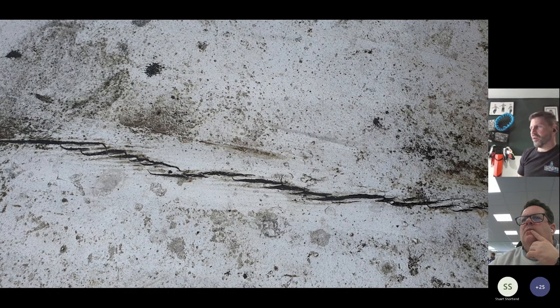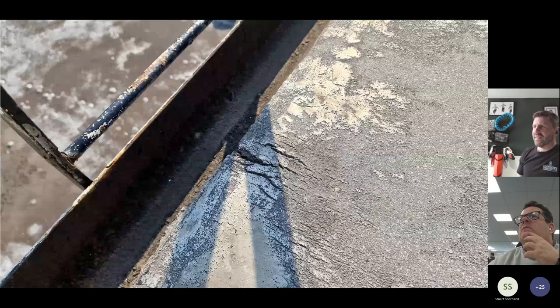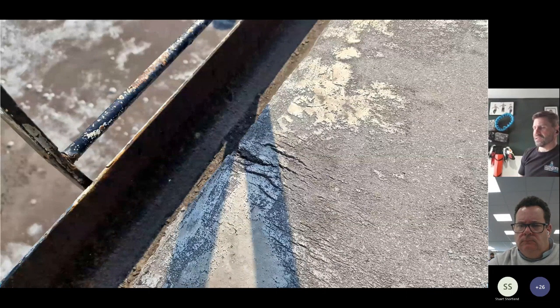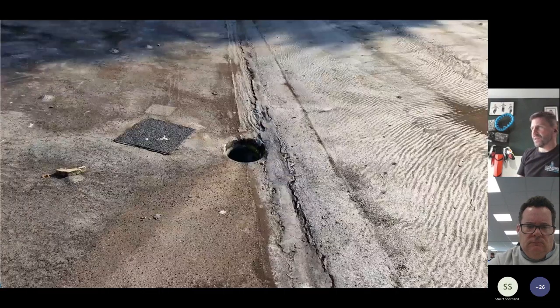Cracks is another common occurrence in asphalt, and again, like with the felt systems, it's down to a couple of reasons: structural movement, thermal movement, and the smaller cracks, as you can see in this picture, is down to lack of protection from the UV. Those trims that are on the edge there at the drip detail have expanded and contracted, and that's what's caused these cracks here.